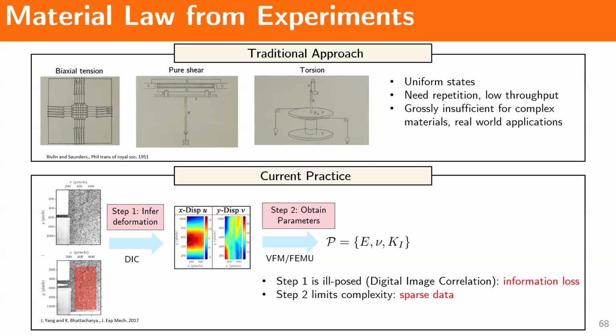And then the second step is usually done with the virtual fields method, or VFM here. And limitations in the analysis part here also lead you to only be able to do idealized experiments, so things like uniaxial tension, biaxial experiments that have rather idealized geometry. And so this leads you to sparse data, because once you have complex states, these methods tend to fail, or have basically large error when you have holes or when you have fracture in the material.